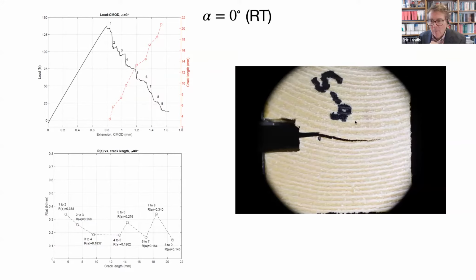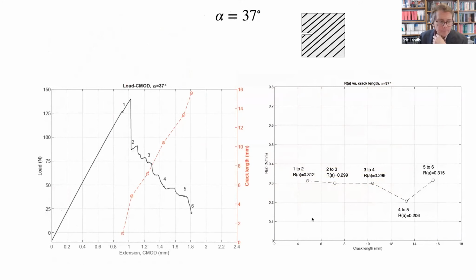It's not necessarily obvious from the image, but you definitely see the early wood, late wood sections. In this image, the light areas are the late wood, the darker sections are the early wood. And this is exactly what we would expect, that we have these thin cell walls, bigger cells. We would expect that to be the path of least resistance. So now if we turn the specimen, this angle is 37 degrees. We see some instabilities in crack growth, at least initially, relatively constant resistance.